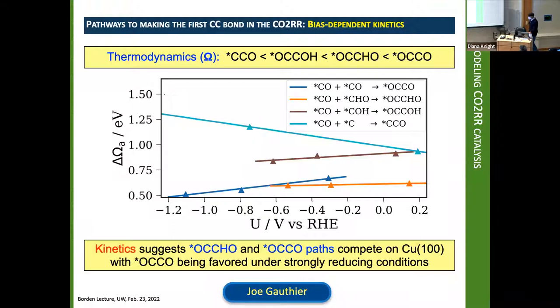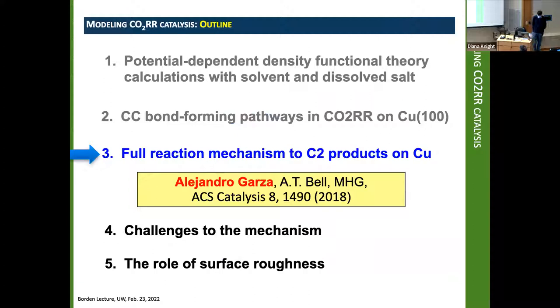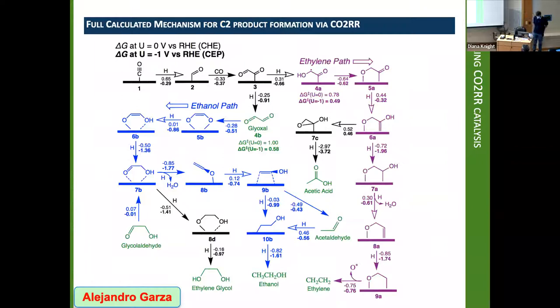Okay, so in fact, we can really make some predictions here, and some of these predictions, especially the role of CO recombination, seem to be consistent with the most recent experimental results. Well, you can then go further, and our attempt to put together a full reaction mechanism will just give you a hint of the complexity here. And this was a tour de force by Alejandro Garza, who was a joint postdoc between Alex Bell, my collaborator, and me. This is a summary of a mountain of work.